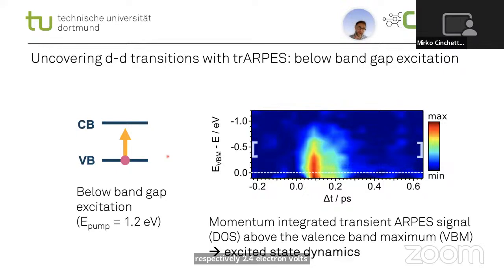So let me now explain what we see on this slide. This is the momentum integrated photoemission intensity that we measure in a time-resolved experiment when we excite FePS3 below the band gap. You see here that we have this enhancement of the photoemission intensity around 0 femtosecond. So this is when pump and probe overlap. And this plot basically gives you the density of states of the excited state. These energies are the energies above the valence band maximum.